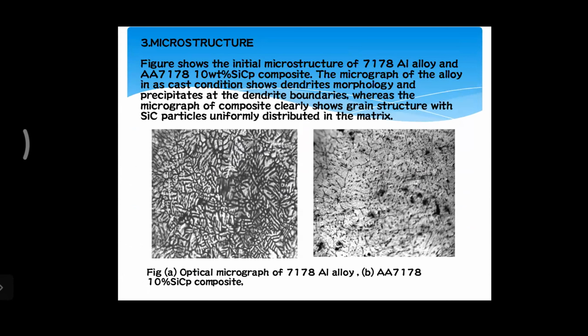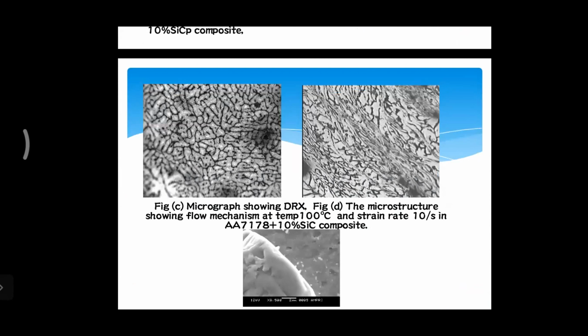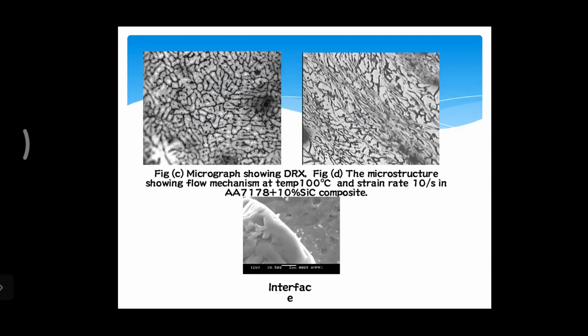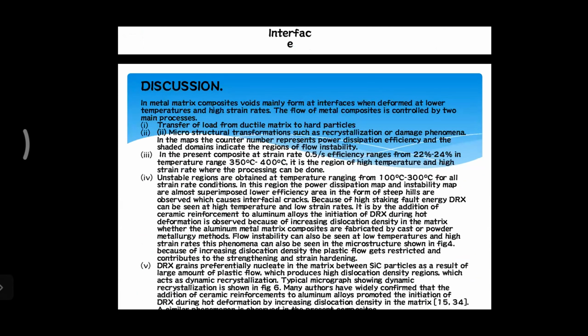The lower micrographs show DRX, where the grains are refined and reduced to smaller size. At higher strain rate, the flow of the material shows the mechanism at 100 degrees centigrade and strain rate 10, showing dynamic recrystallization or recovery of the material. The SEM micrograph shows the interface, how the SiC particle and the aluminum matrix are well bonded. The discussion part is the transfer of load from the ductile matrix to the hard